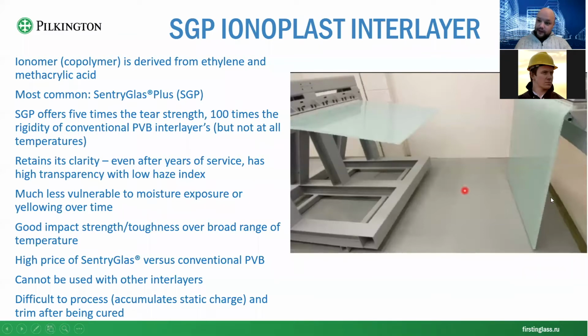We will see the videos, but now watch the picture on the right, the photo. These are two tempered laminated glasses where the glasses are broken in both cases. On the right, there is a conventional PVB. On the left, there's Ionoplast. You see, it is still holding almost horizontally. So the interlayer has its own capacity to carry the load. It is only the interlayer that is holding it in the horizontal position, not letting it drop like a normal PVB.